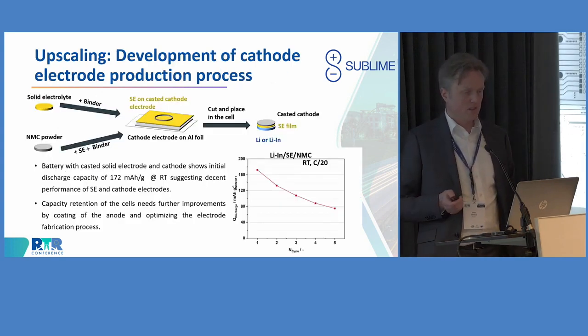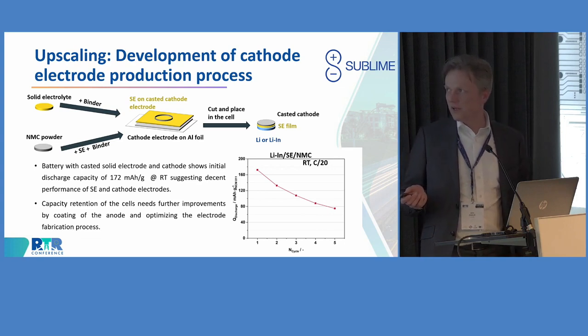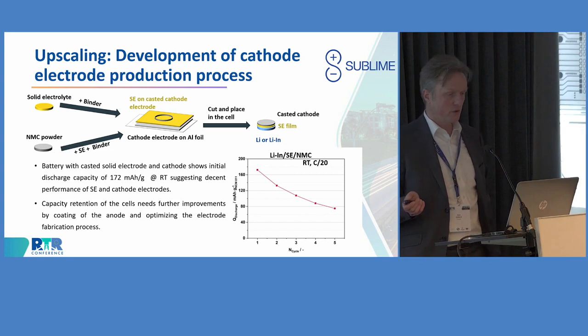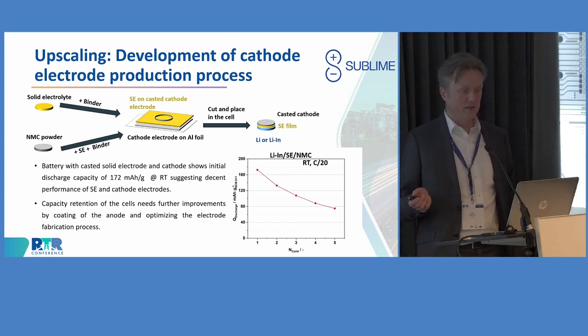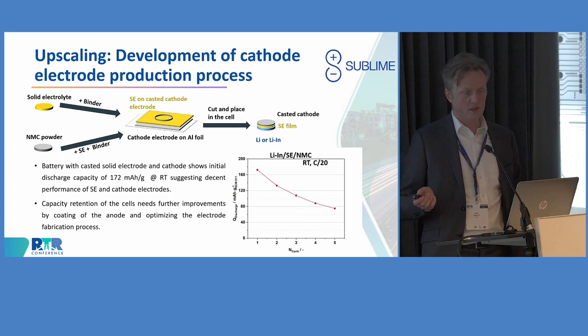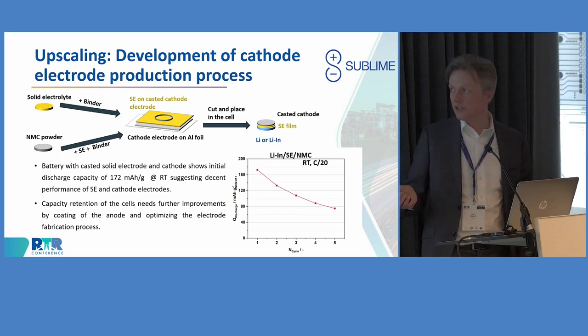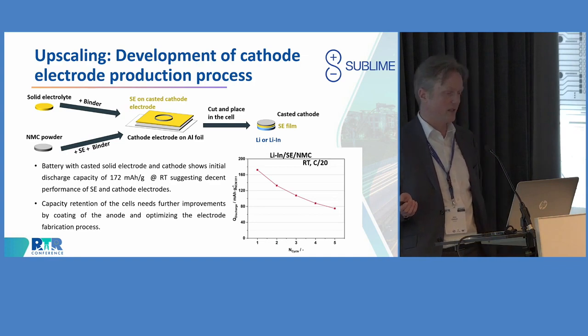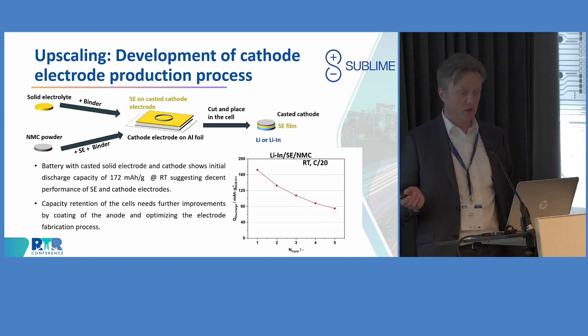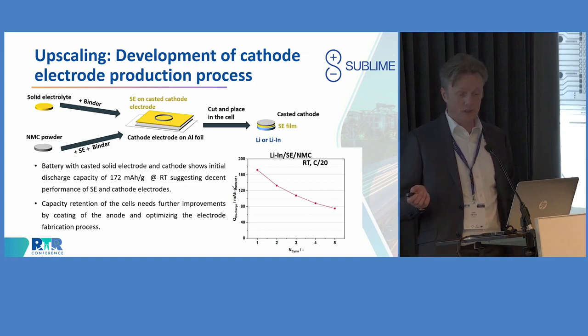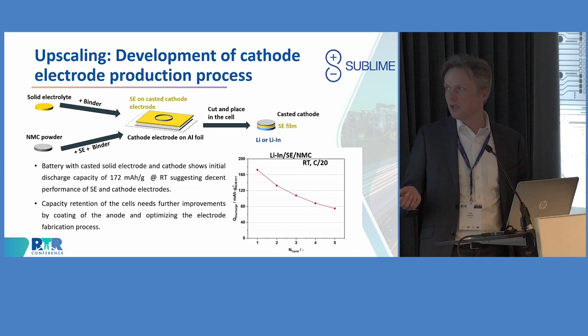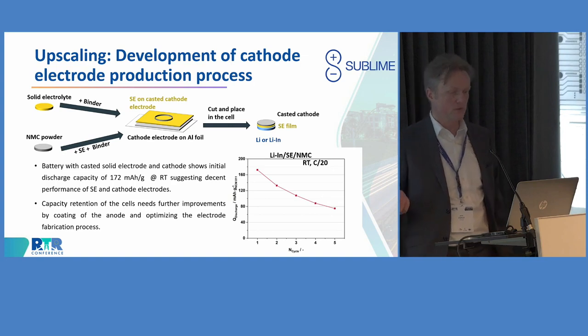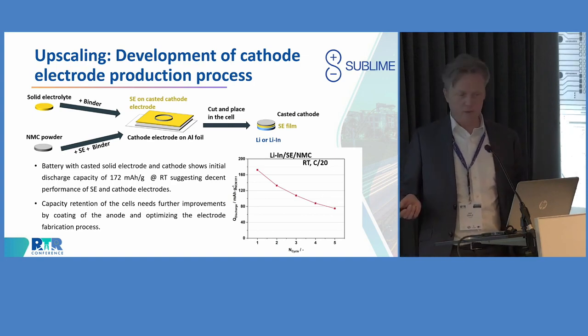So while we are still further optimizing on the coin cell level, the electrode, on the anode side, we can then further proceed with working towards the pouch cells with regards to the solid electrolyte and the cathode processing. So this is also then being done, and it's working. We see already here that we are able to reach a very decent initial discharge capacity of that one. You remember that I showed 195 milliampere hours per gram of active material before, so that's just slightly below this. So next technology brick, we can further optimize.